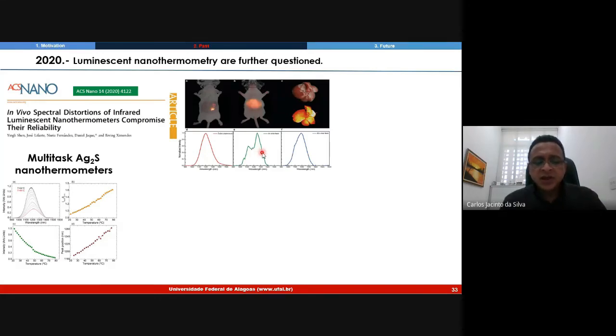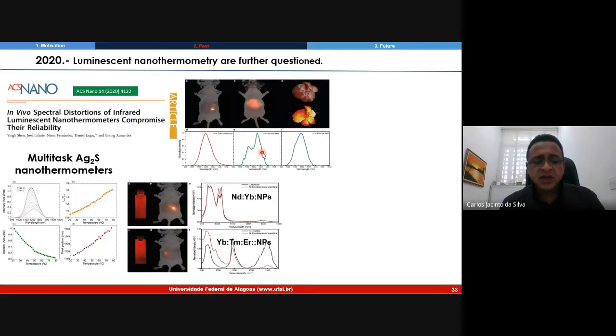These results clearly demonstrate that the tissue-induced spectral distortion cannot be neglected when interpreting infrared in vivo fluorescence images. Otherwise, the analysis could lead to erroneous conclusions. The same spectral distortion also occurs with highly doped ion nanocrystals like neodymium-doped nanoparticles and thulium-doped nanoparticles. Look here, the spectral distortion in a cuvette and subcutaneous.